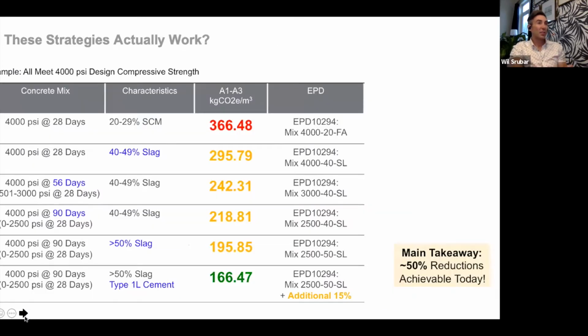What I wanted to do, just as a quick summary, so Chris and I were part of a consulting project, and we presented this to the client, but this demonstrates the reductions that are achievable by implementing those 3 best practices by using a concrete mix that exhibits a 4,000 PSI design compressive strength. All of these mixes here will ultimately meet that design compressive strength of 4,000 PSI, but you can see that